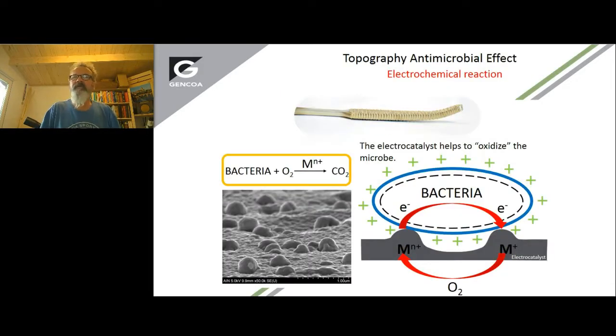How does our surface kill a bug? Well, it's going back to my laws of physics. If you generate surfaces which have a very low radius of curvature, where you have electrons, then you can generate extremely high nano-scaled electric fields. And if you have a bug or a bacteria in contact with this surface, then anything that's between the bug and the surface will act as an electrolyte to set up a voltage, which will extract electrons and potential metal ions from our surface. These hot electrons and metal ions are very, very disruptive to cell walls, DNA, RNA. They can be so disruptive that there's no resistance built up to such a mechanism.